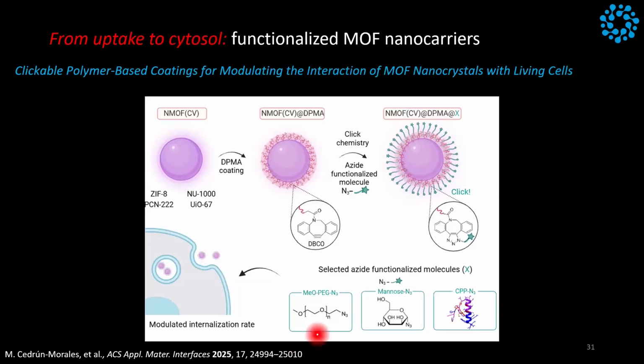So this is a work of Manuela again. Basically, I asked her to compare. So she did a research stay with David Fairen-Jimenez in Cambridge, and she was working with this PCN222 and working in PEGylation. And basically, what David developed is that phosphates interact a lot with the zirconium cluster that you have in this MOF. So it's a kind of click reaction that you can functionalize them with DNA, PEG ended in phosphates and so on. It's very straightforward with anything more or less.